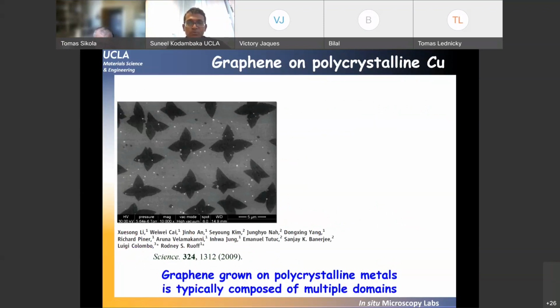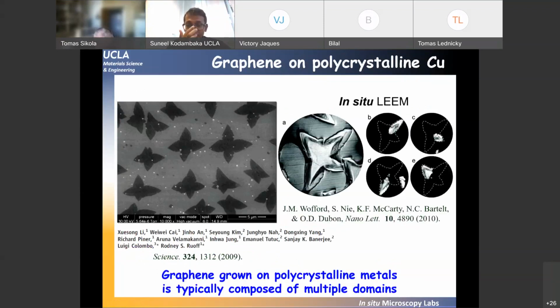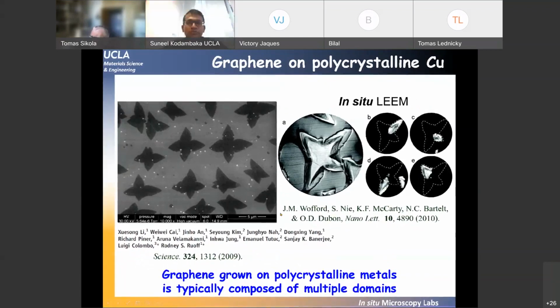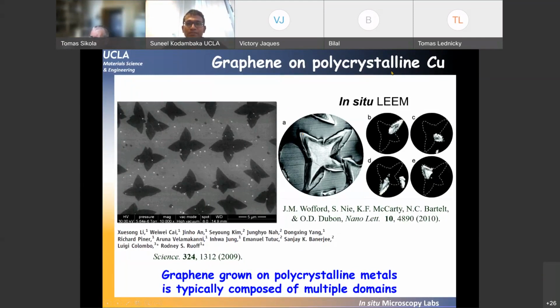And our motivation for this study, for those of you who are familiar with this topic, is that when you grow graphene using any of the hydrocarbons on typical metals, which is usually polycrystalline, you end up with polycrystalline or polydomain graphene. And this is cold-rolled copper, so it has a 001 texture. When you grow graphene on 001 oriented copper, you end up with these four-fold symmetric graphene domains. And this is a LEEM image showing that you have these four different domains.